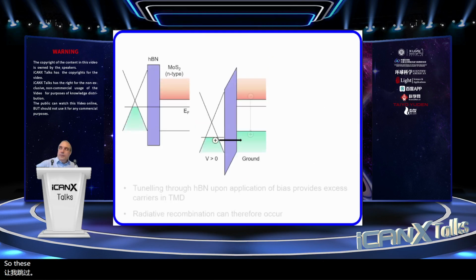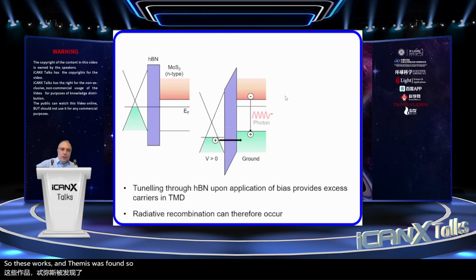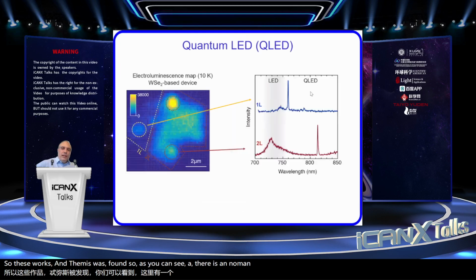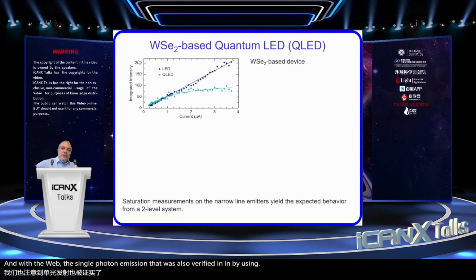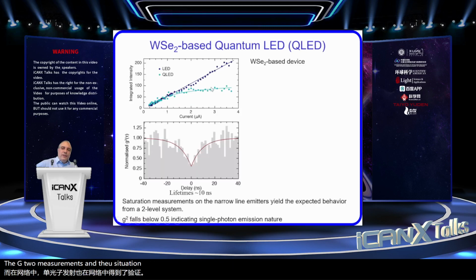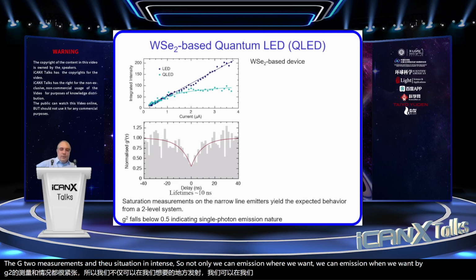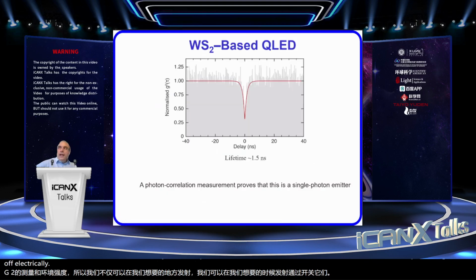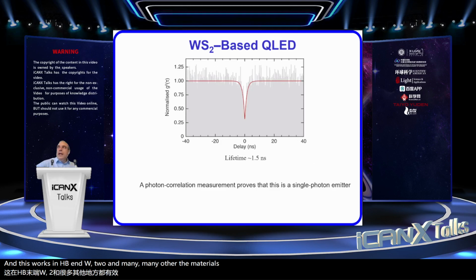So this works, and the emission was found. As you can see here, there is a normal LED and a QLED structure, and we do have the single photon emission that was also verified by using the G2 measurements and the saturation intensity. So not only can we get emission where we want, we can get emission when we want by switching them on and off electrically. And this works in hBN, WS2, and many, many other materials. And that's it. At the moment, I will just stop here.